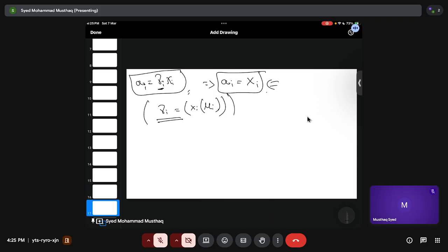This activity coefficient depends upon the interaction between your cations and also the interaction between your anions. Now there are many models. One of them is the Temkin model. In the Temkin model, you should also involve the configurational entropy, so we have an assumption called random mixing.